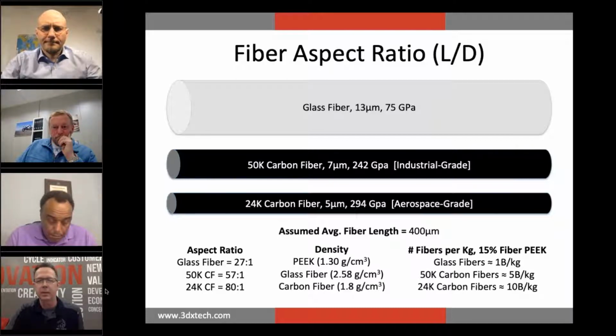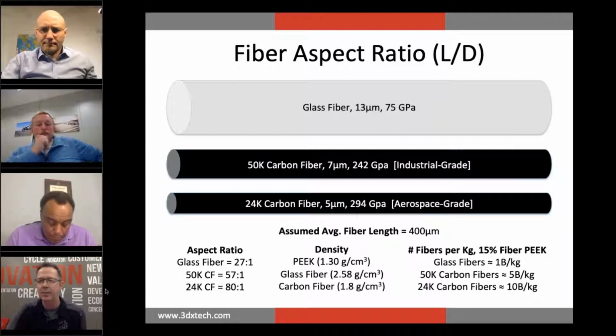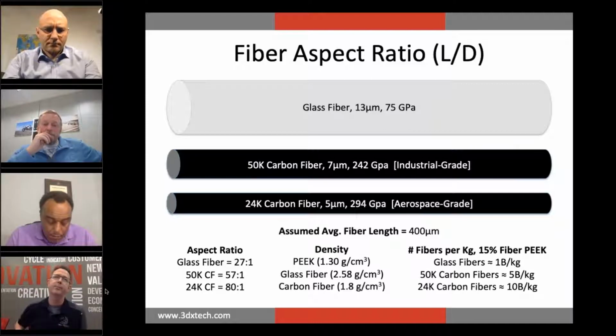These fibers are drawn to scale, essentially, where the typical glass fiber that's used in composites is about 13 microns in diameter and has about a 75 gigapascal modulus, so the stiffness. Compare that to the two carbon fibers, the 50K or the industrial grade carbon fiber. It's a smaller diameter and significantly stiffer, and even smaller diameter is 5 microns and almost 300 gigapascals for the aerospace grade. And where this comes into play is not just cost, and so the next slide you'll kind of see the difference.